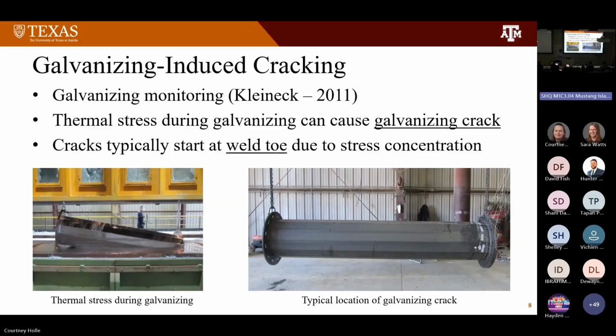And some researchers have also focused on the galvanizing process, which can introduce thermal stress. The research shows that a high level of stress concentration occurs at the weld toe during the galvanizing process and can cause galvanizing cracks, which means the weld toe is a critical weak area even before the structure is put into service.